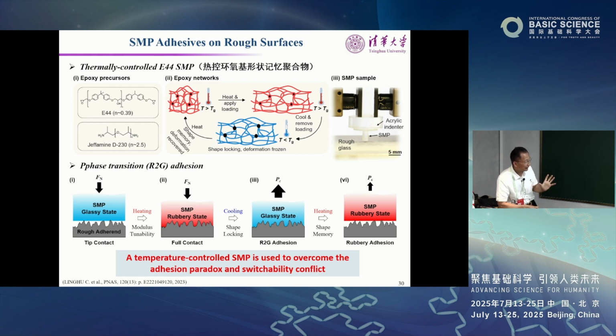Now, if you want to release, then you just heat it up. Simply, you heat it up. You wake up the elastic energy stored near the interface. The material will spontaneously rebound. Okay, so this is the key. You do a temperature cycle. You press at a high temperature, you cool it down, you have very super strong adhesion. Then you can release it by heating. Just simply heat.